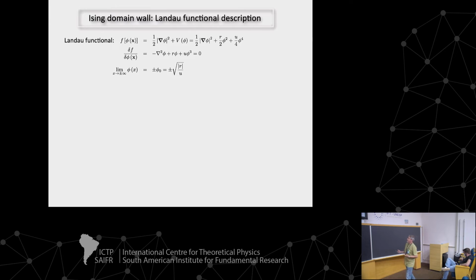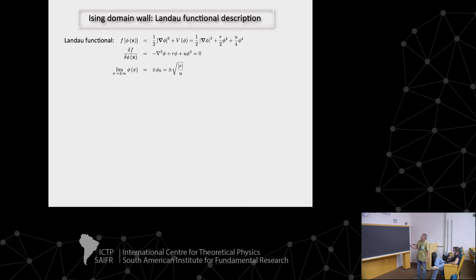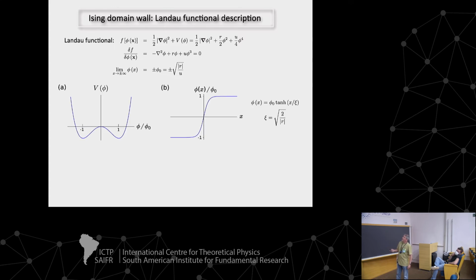where you have a very good description with a mean field description with Landau theory, where you have the so-called Landau functional. When r goes to 0, you go through the phase transition. You have the quartic term. You have a term that penalizes spatial fluctuations. And you can solve this model, this Landau functional. In other words, you can minimize for phi, the order parameter phi, as you cross from one phase to the other. So this is the Landau potential.